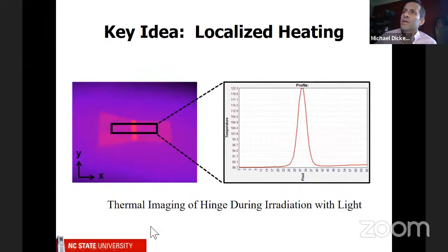And the glass transition temperature of the polymer is about 100. So what we're doing is taking the polymer and heating its surface above its glass transition temperature, but only in the region where the ink is located. The rest of it is below the glass transition temperature and remains stiff.